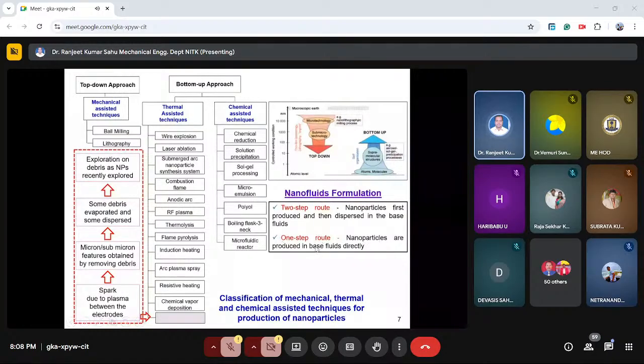So this one-step route or single-step route can offer various benefits as compared to the two-step route. What are the benefits? It avoids the process of drying, storage, transportation, and redispersion of nanoparticles. As a result, the production cost will be reduced. Also, in a single-step route, the nanoparticles are produced directly in the base fluid. If those materials are of high conductivity and more prone to oxidation, it can prevent the formation of the oxide film on the particle surface. This is one of the important leads for this one-step route.